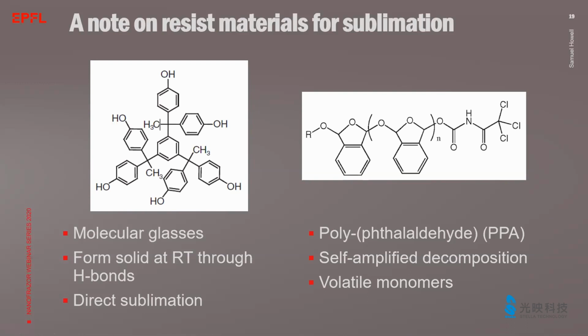good resist for nanofabrication. And the second material, polyphthalaldehyde, which is a polymer that decomposes by a self-amplified decomposition reaction, provides a much cleaner way of removing it from the surface. Due to this special self-amplified decomposition, the polymer decomposes differently than normal polymers such as PMMA via a rapid decomposition process, and it decomposes into volatile monomers without melting. This is important because this reduces the contamination on the tip apex.